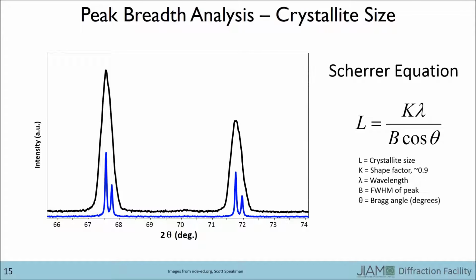This equation appears so simple, but you can't let the simplicity tempt you to use it with less consideration than you should. For instance, based off of what I have told you so far, you would think that the sample that produced the black curve should have a much smaller crystallite size than the sample that produced the blue curve. Surprisingly, both patterns were made with the same sample. The difference is that different diffractometers and optics were used. This illustrates the fact that there is some inherent instrumental broadening of the data you collect related to the incident and diffracted beam optics that must be accounted for before further analysis.